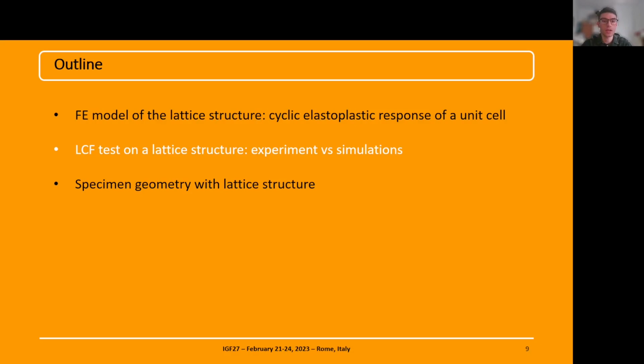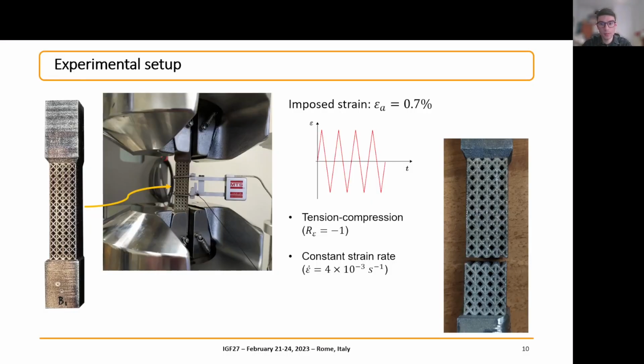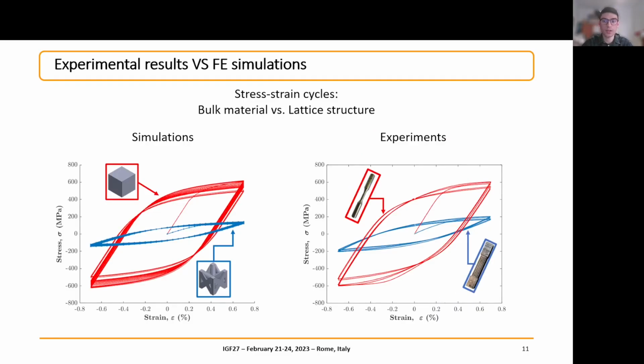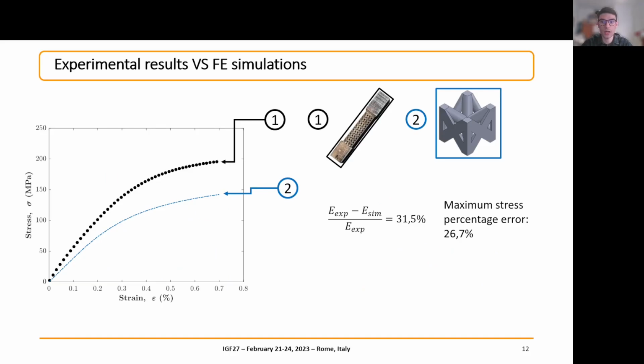So at this point, I'd like to present the results obtained by testing one of the lattice specimens that I showed you before. This is the experimental setup, basically the same one used for the bulk specimens. We carried out a standard low cycle fatigue test imposing a 0.7% strain amplitude under symmetric tension compression. And as you can see, the specimen failed near the middle zone. Concerning the experimental results, here on the right I reported the stress strain cycles for both the bulk and lattice specimens. If we compare this data to the simulated behavior, which I reported on the left, the lattice structure response is quite similar. Despite this strong similarity, if we take a better look, the simulation using a single unit cell gives a significant error with respect to the experimental data.